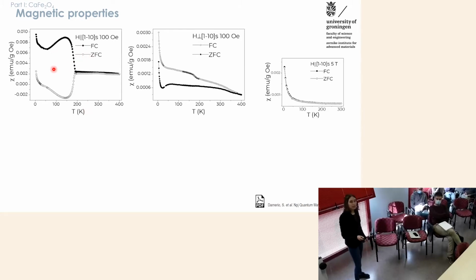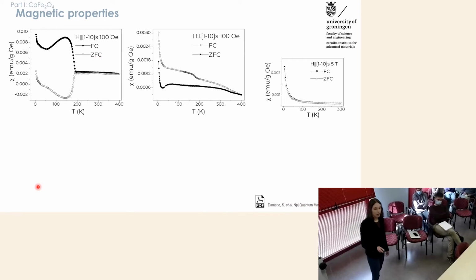And what we see is, you can see here a plot of the susceptibility as a function of temperature. And there is mostly one magnetic transition at around 185 Kelvin. And there is this very characteristic large splitting between the zero field cooled and the field cooled curves. And this usually indicates some irreversible process. It's something that is typical of spin glasses, but usually the splitting temperature is much lower. It is not the Néel temperature. While here we are already splitting at the Néel temperature, if not even higher.